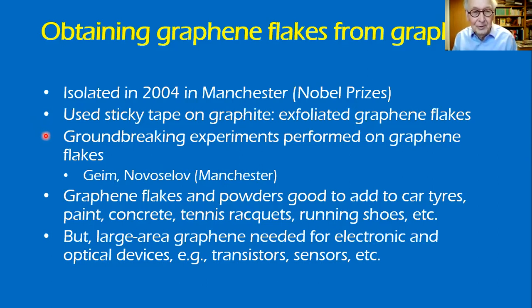And then they performed experiments on this. And these experiments are really difficult because a monolayer graphene is transparent. So just think you've got this monolayer graphene on a piece of sticky tape and you can't see it. But they did experiments. They measured the mobility of the carriers in graphene, and they measured the electrical conductivity. And it's brilliant experiments to actually put electrodes onto something you couldn't see. So some people say they got the Nobel Prize for using sticky tape. Well, no, they didn't. They got the Nobel Prize for using sticky tape and then doing these experiments.